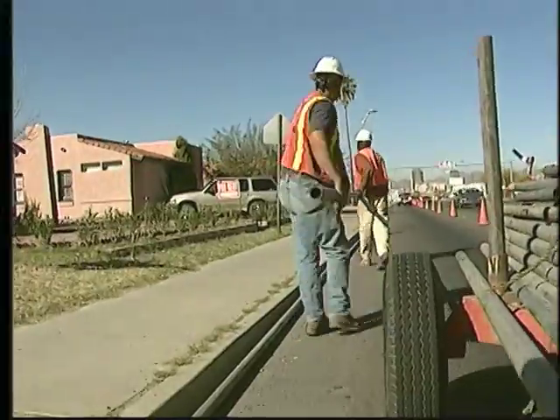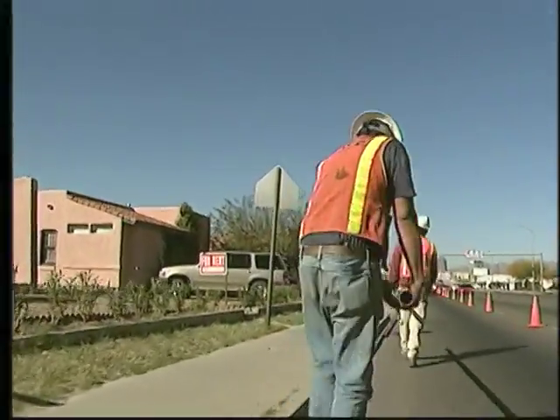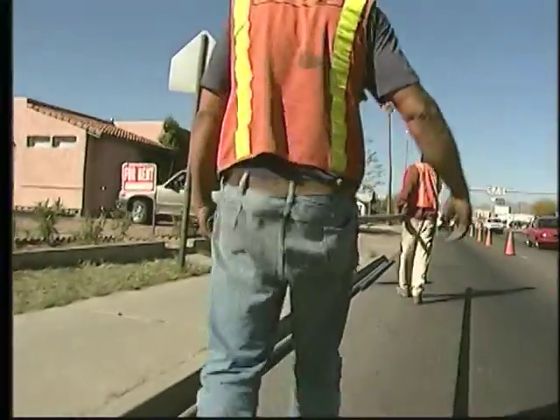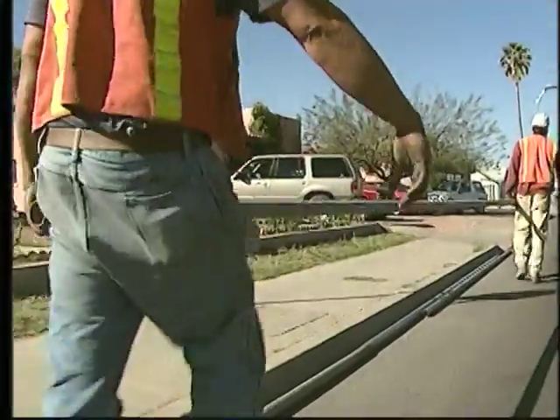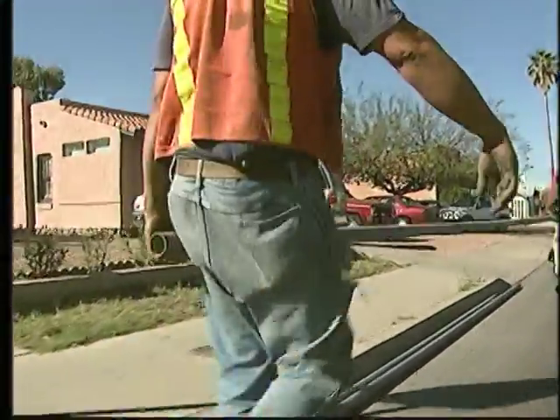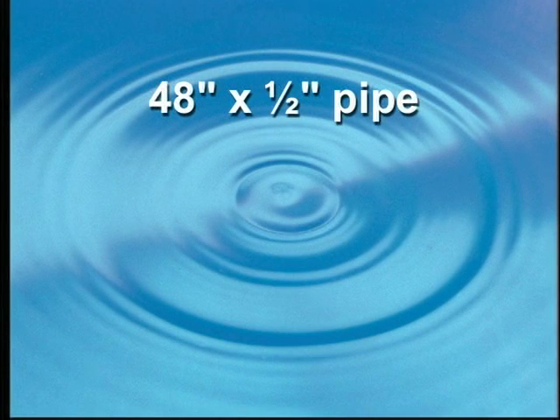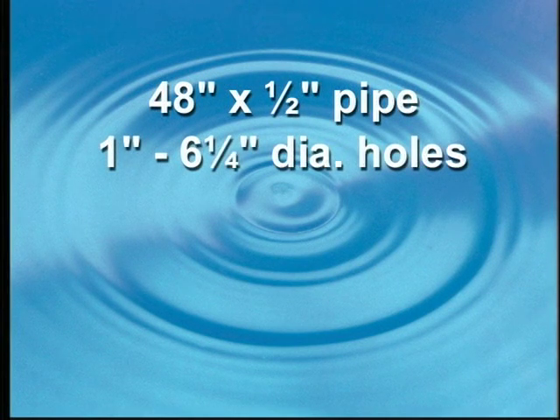The City of Detroit Department of Water Supply subjected a cement mortar lining to a rigorous series of tests to observe its behavior under stress and internal pressures. The City of Detroit, Michigan conducted a pressure test on a length of 48-inch diameter by half-inch wall riveted steel pipe. The section to be tested was perforated with numerous holes from 1 inch to 6 1/4 inches in diameter.